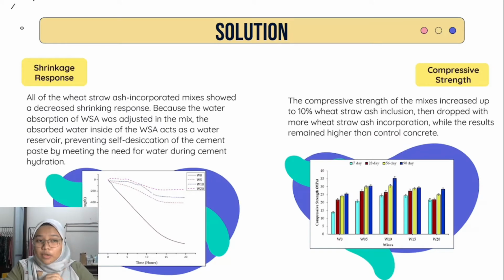For shrinkage response, we can see on the graph that all the wheat straw ash concrete mixes show a decreased shrinkage response. This is because the water absorbed inside the WSA acts as a water reservoir, preventing self-desiccation of the cement paste by meeting the need of water during cement hydration. For compressive strength, the compressive strength of the mix increases up to 10% with straw ash inclusion, then drops with more straw ash incorporation, while the result remained higher than control concrete.